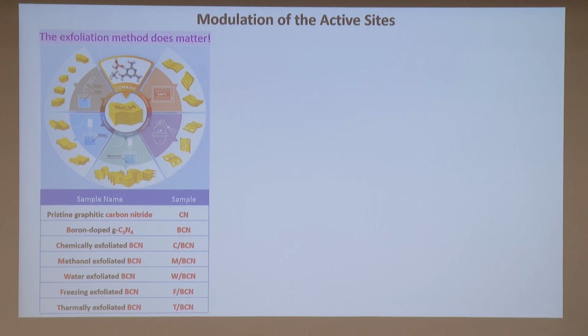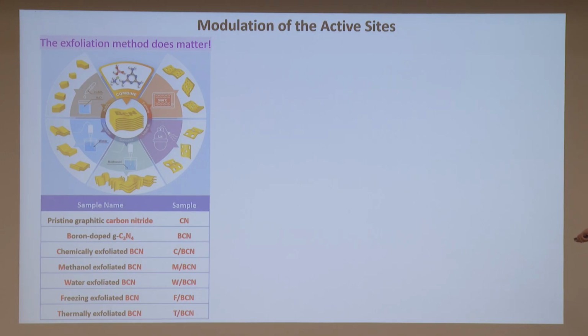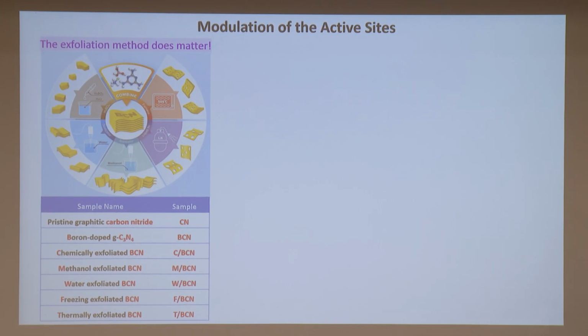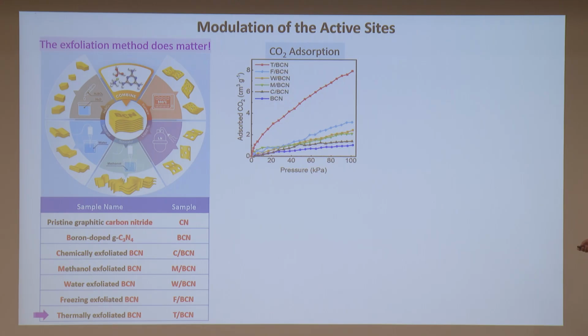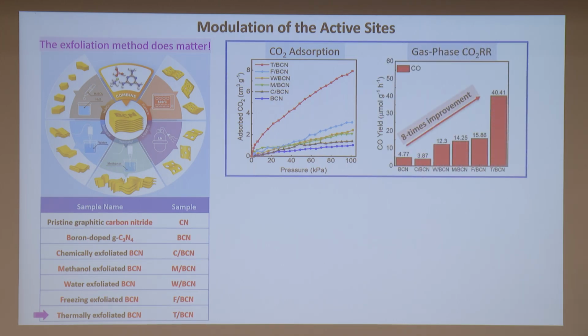Because of the time limitation, I really have to fly, but I will give just the major observation on each slide in 30 seconds. Actually, a lot of detail in material processing does matter. In this case, even when we made carbon nitride with different doping, once we try to exfoliate the bulk form into the thin sheet form, the way of exfoliation also matters. This is a case that shows a significant effect of exfoliation. If it's thermally exfoliated, you increase the CO2 adsorption, you increase the surface area, and you increase the number of active sites. This is reflected in the final result of the thermally exfoliated one: you got 8 times improvement. Very significant. So the material scientist is important.